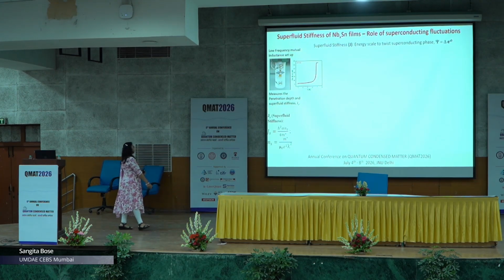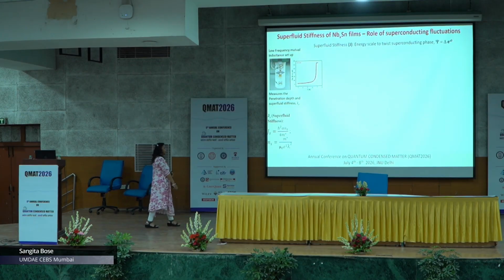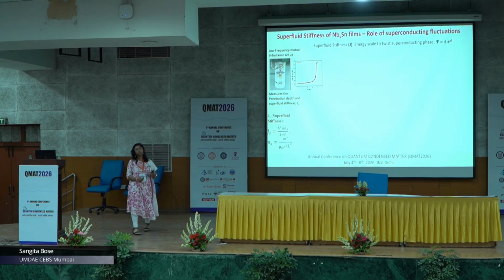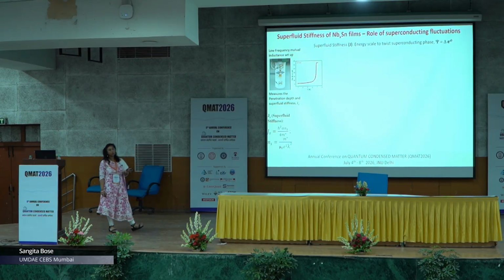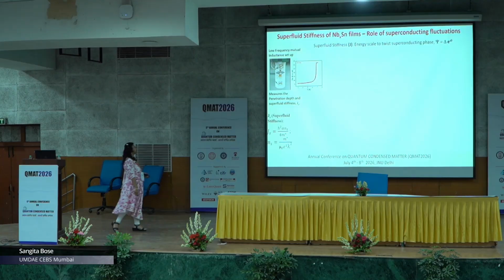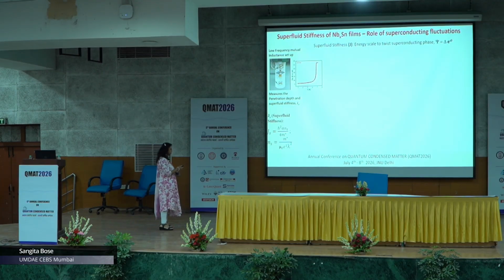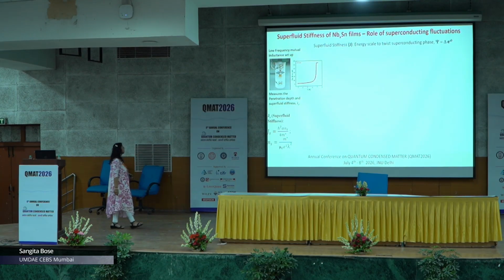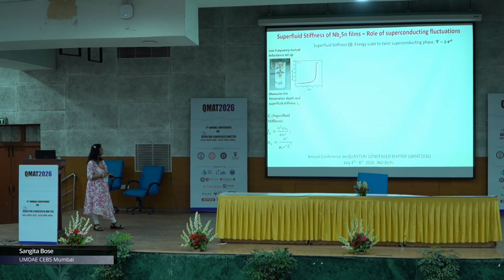Okay. So, what we want to explain is the superconductor insulator transitions which we have observed in these films, and therefore we need to know whether there is any role of superconducting fluctuations. For that we need to measure the superfluid stiffness, which is the energy scale to twist the superconducting phase, and we use the low frequency mutual inductance setup to do this.